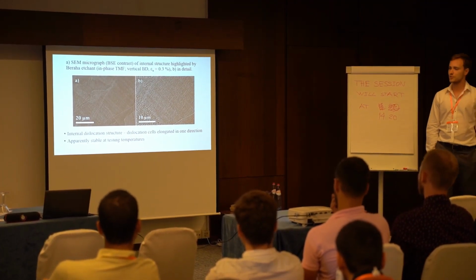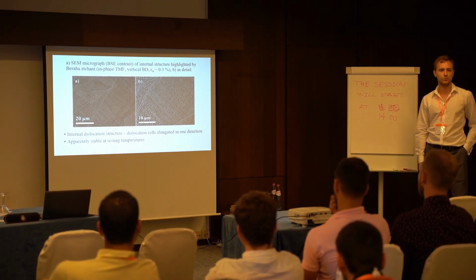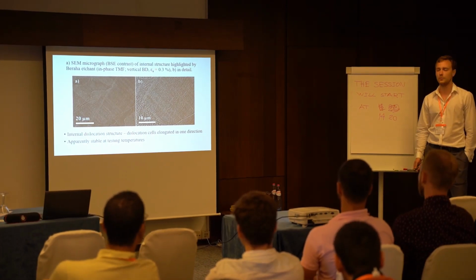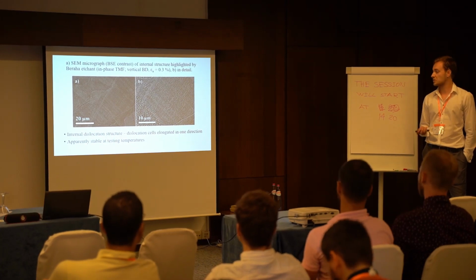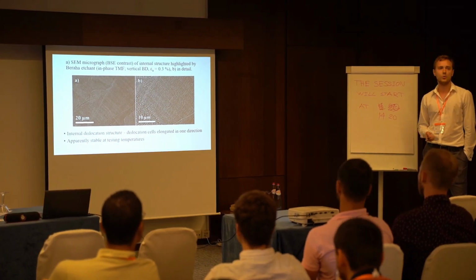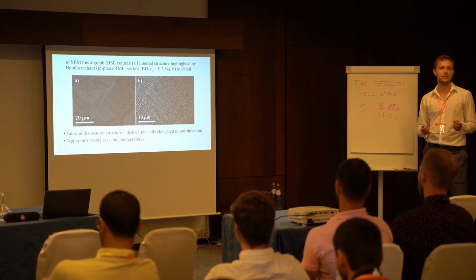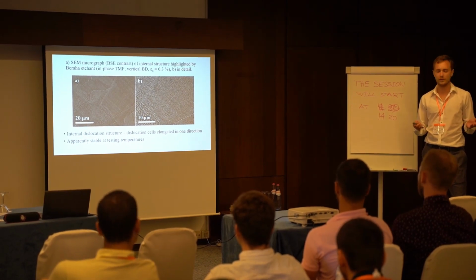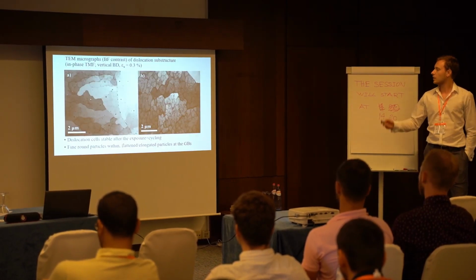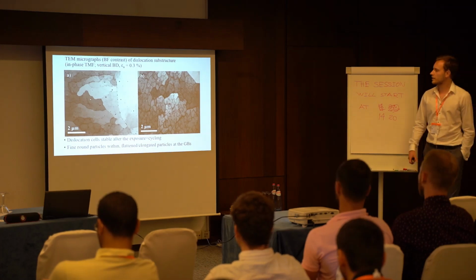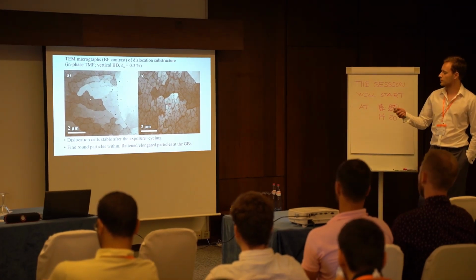Interestingly, the dislocation structure remained almost unchanged. It was very stable. The cells were still elongated in one direction. The qualitative difference you could notice was that there were more dislocations, obviously. Here is how it looks in TEM. So it was pretty stable.